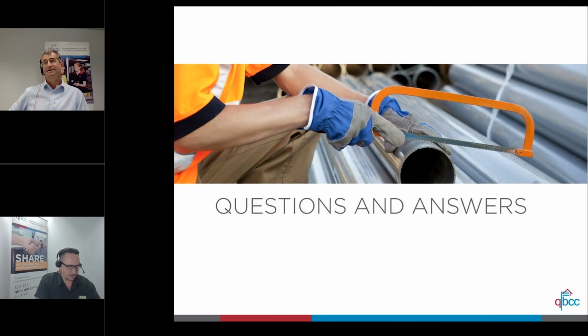Yes. So efflorescence is basically salts that water is carrying through the concrete, and as the water travels up, normally through the sides of the concrete, particularly if you're talking about a garage, that water is traveling in through the side of the concrete and making its way to the surface, and as it evaporates, it's leaving the salts, which is that efflorescence, that white salty finish. So the best way to avoid it is to stop the water getting into the concrete. So if we turn the vapor barrier up around the base of that concrete, then the water can't get through. If the water can't get through, it can't carry those salts through the concrete.